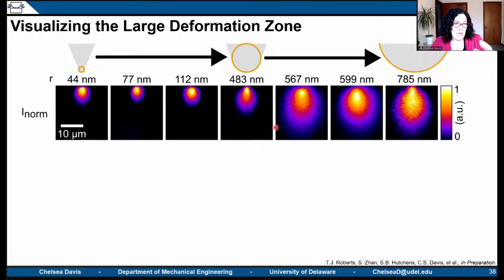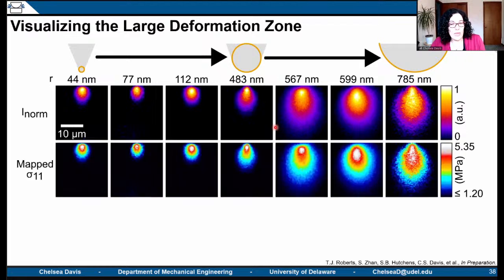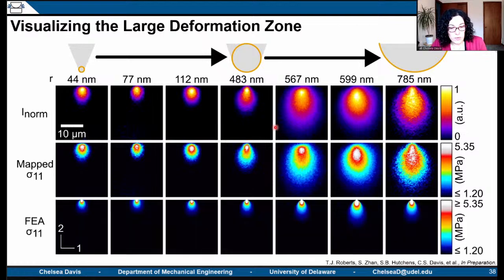So now that we've done this measurement as a function of stress intensity, we can also map the, oh, did I get the wrong image? No, this is right. So if we take our stress to FEA calibration that we have performed and I've talked about ad nauseam, we can then map that and say this is what we think the stresses are quantitatively ahead of the crack tip within our material. And we can confirm this with FEA, where we're showing similar relationships in the increasing size as a function of increasing blade radius or increasing dullness of our blade.